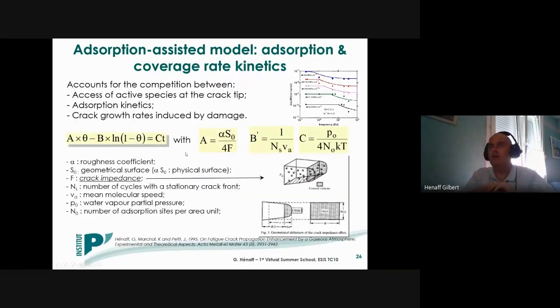And the question is then to determine the variation in this theta value as a function of time for different loading conditions. And for that, we have to write the equation for the access of active species at the crack tip, for the adsorption kinetics, and also take into account the crack growth rates that will in particular control the surface that needs to be covered by adsorbed molecules at the crack tip.